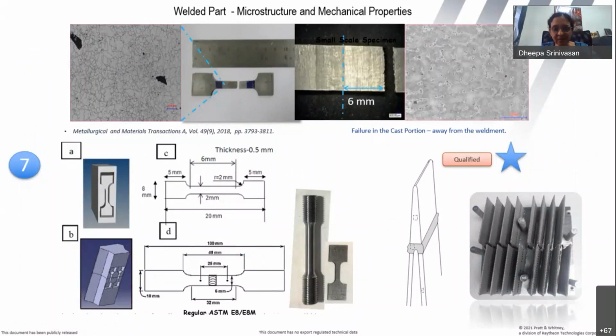So to answer your question, ASTM is coming up with a number of standards, revising them to suit additive manufacturing and small scale testing. And a lot of researchers all over the world, including ourselves, are working on miniature sample testing, not just for room temperature testing, but other ways of testing, not just uniaxial tensile or compression, but for creep, for fatigue, for fatigue crack growth. How do we remodify the whole mechanical testing at temperature to suit the true geometrical requirements imposed by a near net shape manufacturing process? So there is nothing to answer your question. There's nothing that we can fall back on now.